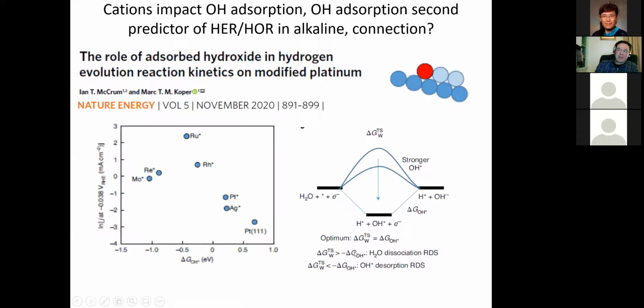Depending on how strongly hydroxide binds, the rate determining step can be the water dissociation. And water dissociation at the surface in alkaline is what gives you the adsorbed hydrogen, making an OH group on the surface. So how strongly OH binds is directly involved in the rate determining step for weak binding metals. For strong binding metals, OH desorption coming off the surface becomes the rate determining step in being able to evolve hydrogen, and therefore OH binding is mechanistically tied.